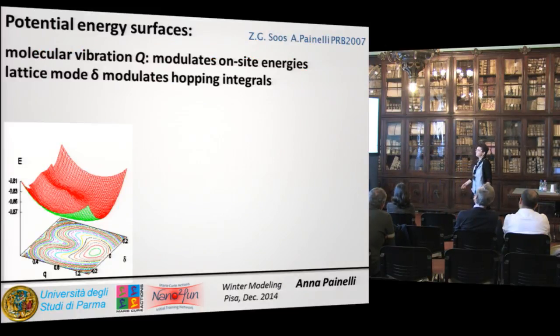So, I have the adiabatic approximation. The first result I can show you is the ground state energy as a function of the coordinate, what everyone calls the potential energy surface. Please look at how anharmonic the system is. We started with harmonic phonons, but the result is wildly anharmonic, and the reason is the coupling with the electrons and the proximity to a phase transition. We are near a phase transition, but the system is stable as a neutral regular stack, delta equal zero.